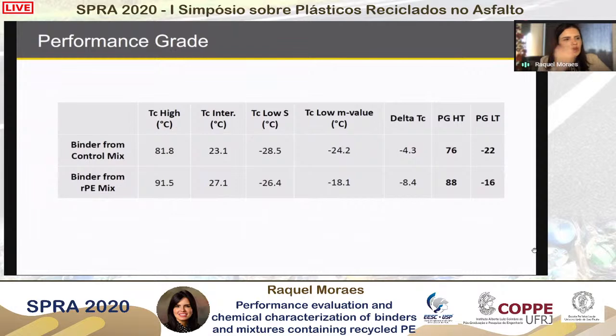And here we have an overall spectrum of the performance grade results of the binder extracted from the control mix and the binder extracted from the mixture containing the recycled plastic. We can see a change in PG grade of 2 grade bumps from 76 to 88, and a decrease in the low temperature PG grade from -22 to -16.